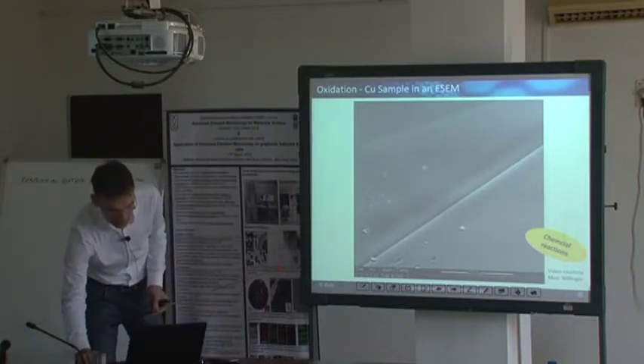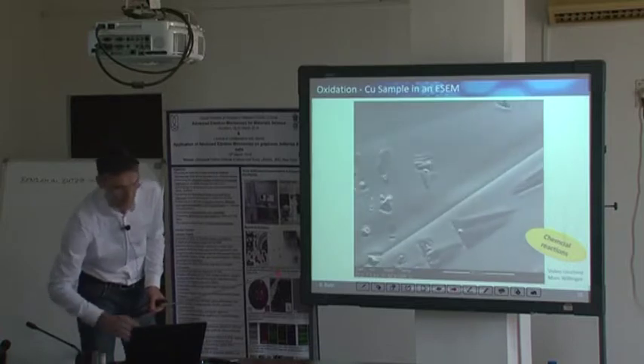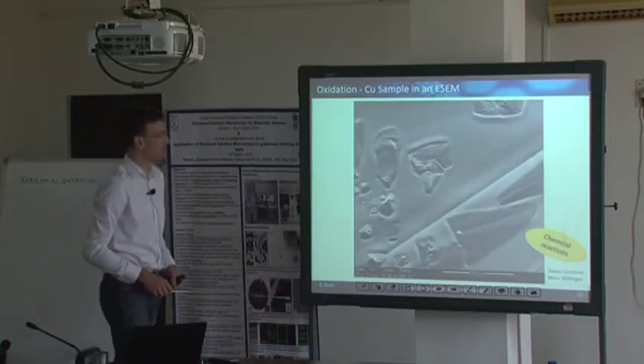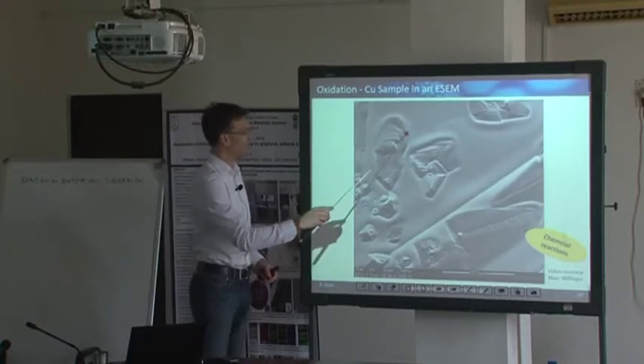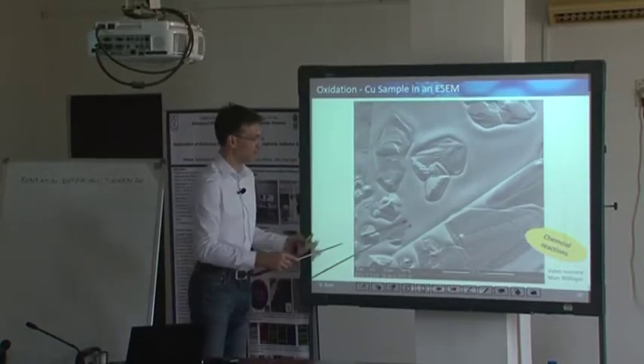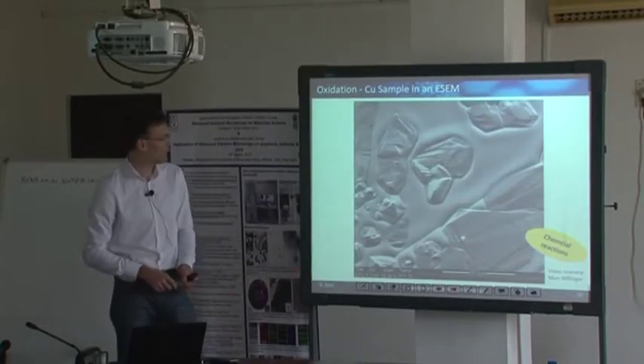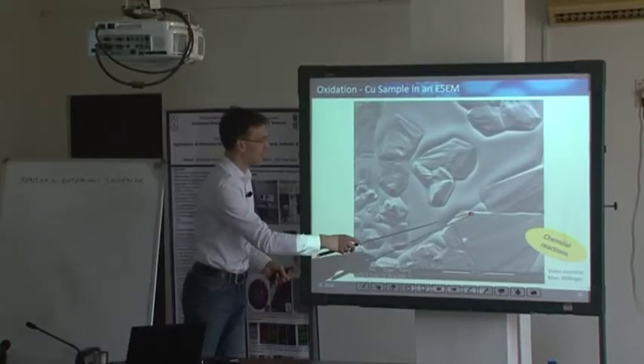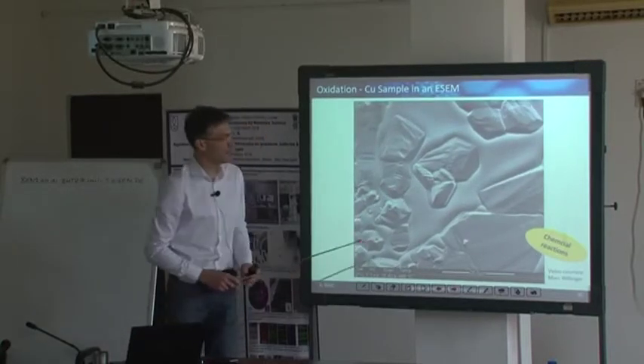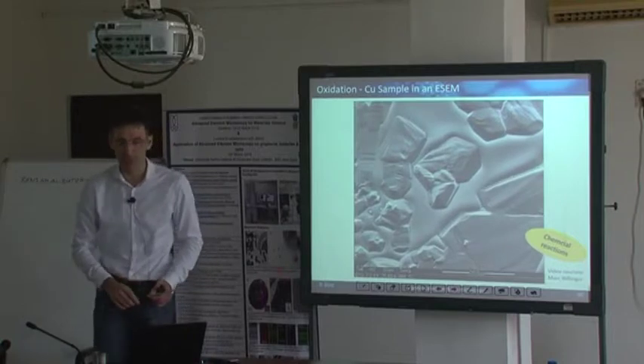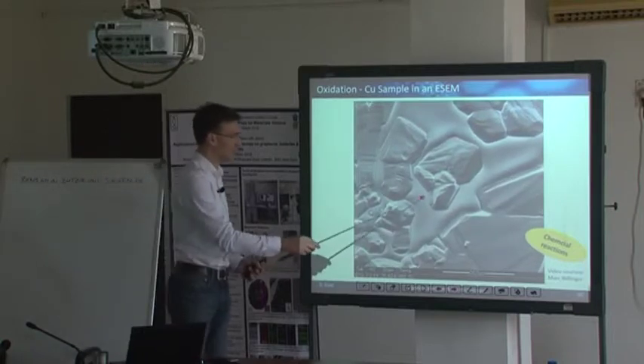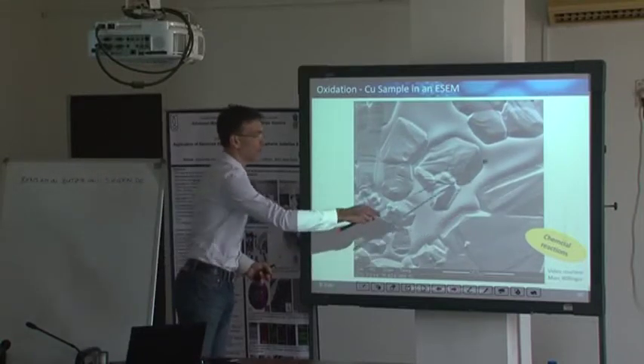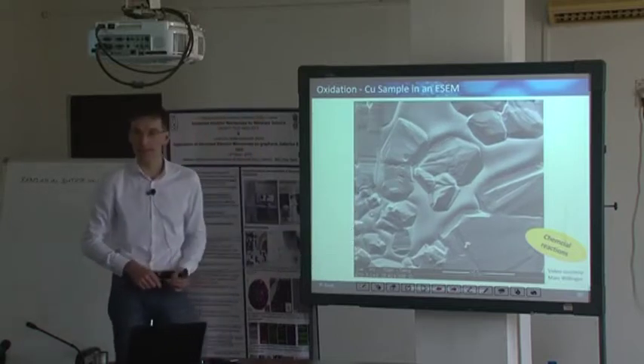And you will see that this does not happen all over the surface. This is the copper oxide that forms on the surface. This is secondary electron imaging mode, and you see this nice growth of all those copper oxide crystallites. In this particular case, up to that state, not the whole surface is oxidized, isn't it?